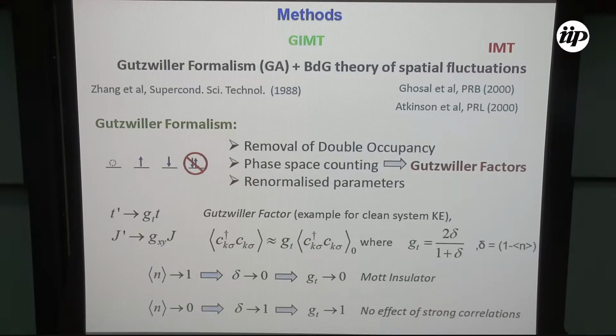Let me give a short introduction to what we are doing in a Gutzwiller approximation. Since the double occupancies are not likely in the sample because the electrons don't like each other, their repulsion is very strong, we take these states out of the Hilbert space. As a result, the parameters in the problem, like the hopping parameter or the J parameter, the superexchange parameter, get renormalized by factors which are called Gutzwiller factors. In a simple-minded approach, you can calculate these Gutzwiller factors using phase space counting arguments, because you have taken some states out of the Hilbert space. So you can calculate this Gutzwiller factor. I will show you for one. Let's look at the kinetic energy term. You have one Gutzwiller factor in front of the normal kinetic energy term.